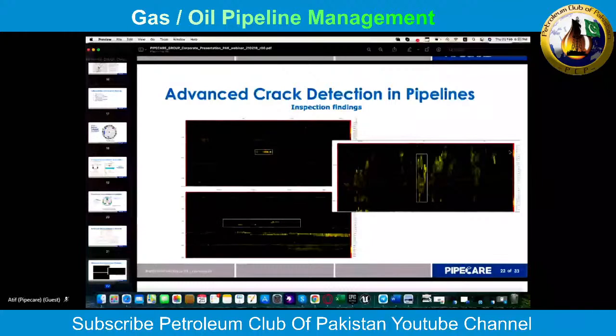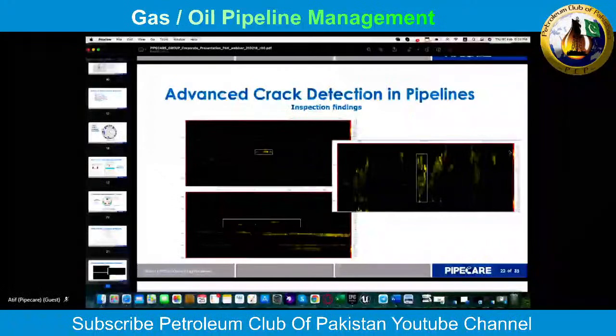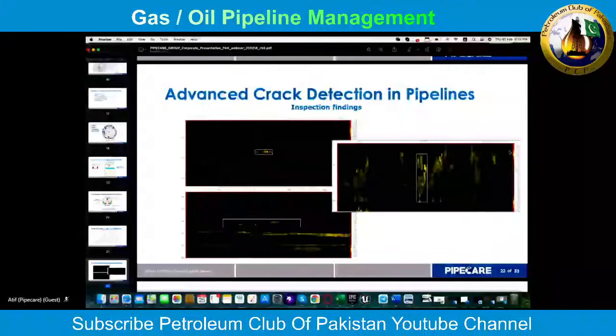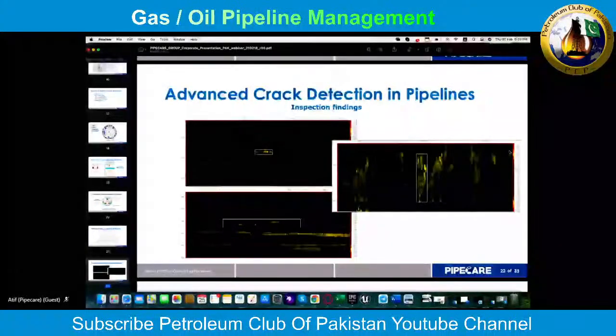These are screenshots from real features, which we found with our crack detection tool. On the left, you see 2 cracks in longitudinal direction. And on the right, you see a crack field in axial direction. As I said, both types of cracks were found with the same tool. Just the orientation of the transducers had to be changed, but we can see the respective cracks. Next.